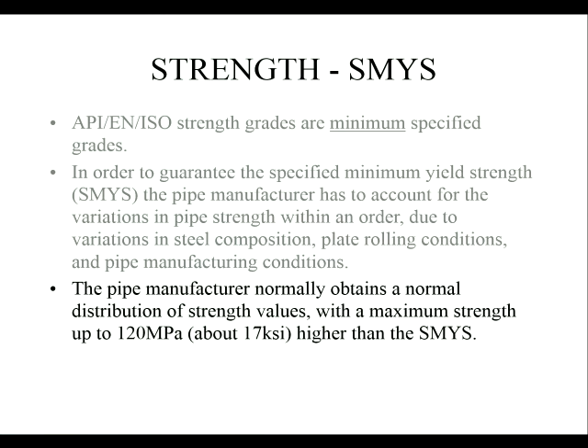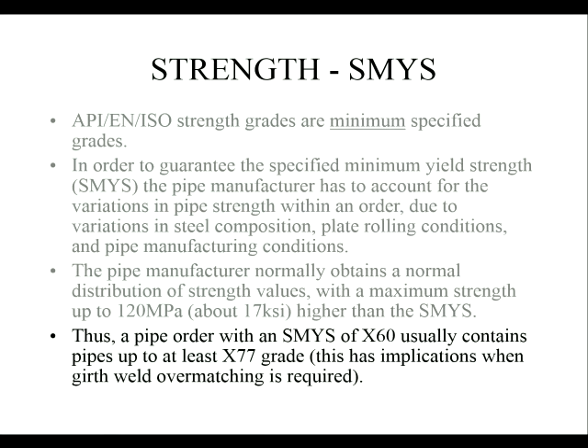The maximum strength may be 120 megapascals more, or 17 KSI, or 17 X units higher than the minimum. So you get quite a distribution of properties. And this can be a problem, because if you're matching your welding properties to the properties of the steel, which one do you match it to? The minimum or the maximum? So that is an issue. So we have this idea that X60 can have some X77 in it, and when we want to weld this, what we want to do is overmatch the weld. That means we want the weld metal to be the strongest thing in the system, so that the weld doesn't fail, the pipe fails.